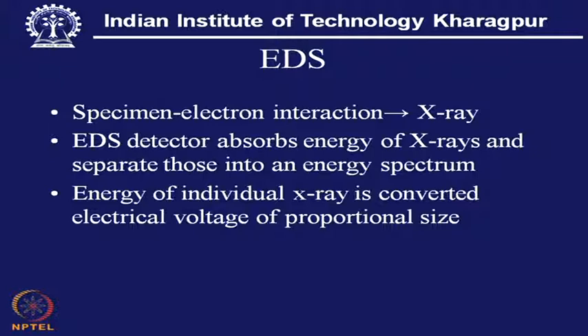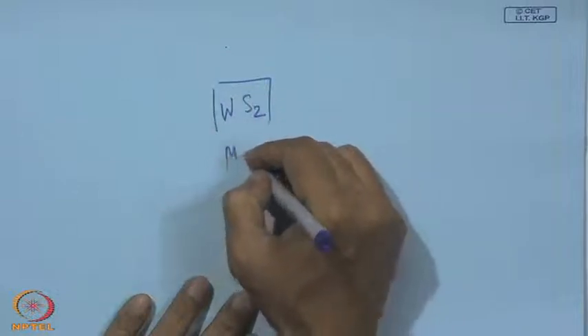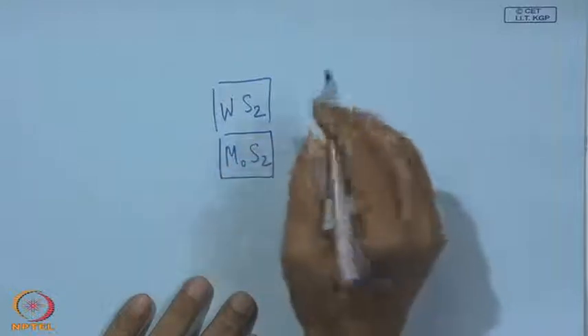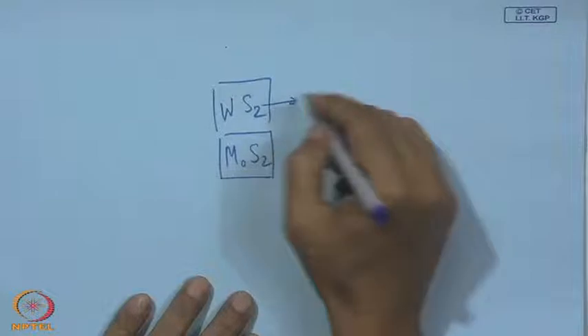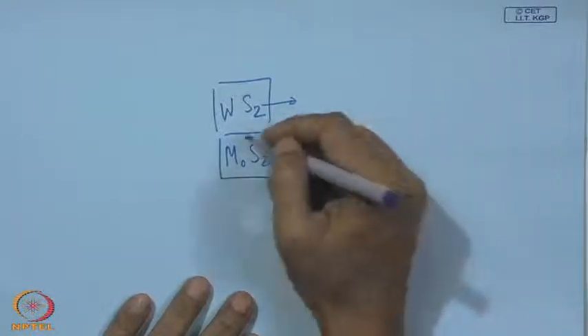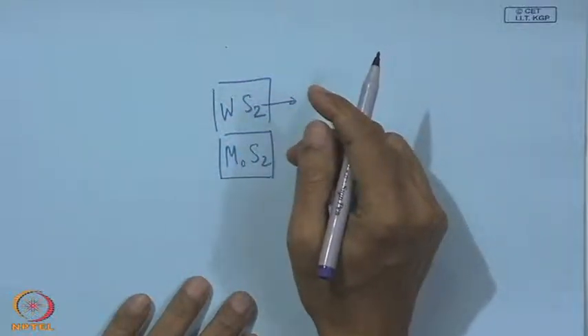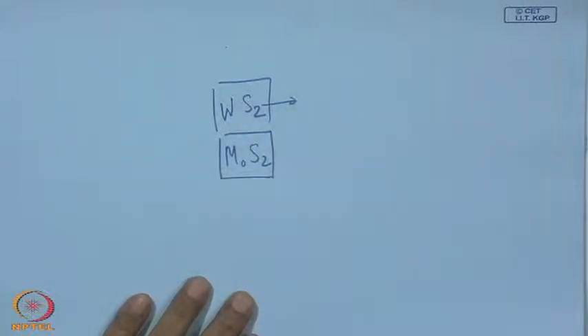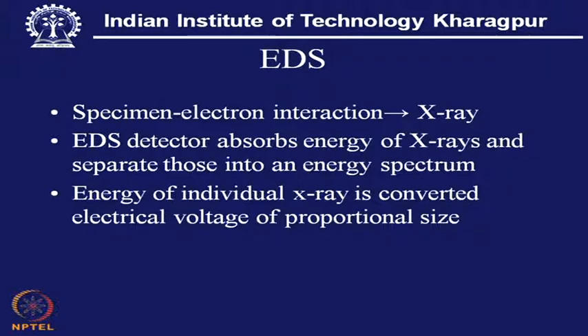Now, in this case, what is important concerning the activity in the coating? So, there are certain things that should be looked into, say for example, its application WS2 coating or molybdenum disulfide coating. Now, these are of immediate interest, but we have also seen that in this case incorporation of oxygen gets into that and that makes this coating inferior and the quality falls drastically. So, whatever may be the issue, detection of oxygen is extremely important. Now, it is a typical application of this EDS or microprobe for this particular coating, that is the detection of oxygen. Just like Raman spectroscopy, which we have illustrated is extremely useful for diamond coating, this is also extremely useful.